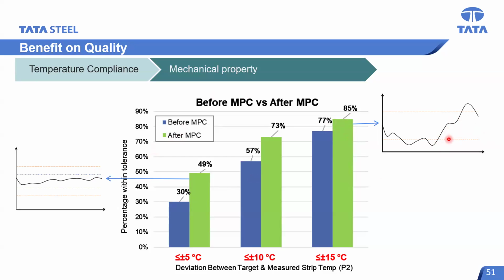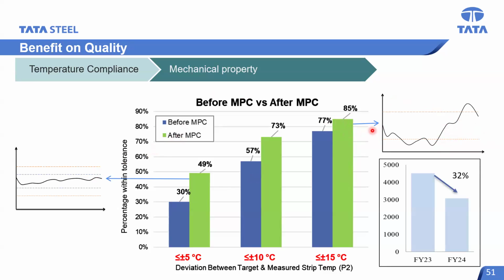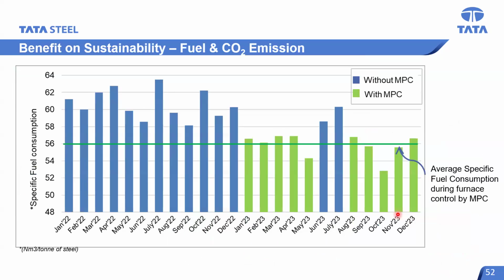Another aspect is whenever in a single coil there is some intermediate portion which is outside this band, and the rest of the coil is good, we do a kind of reprocessing. We take it to another line, cut and remove the non-compliant part, and again dispatch the remaining coil. This reprocessing has reduced by almost 32% between these two successive financial years. These are in tons.